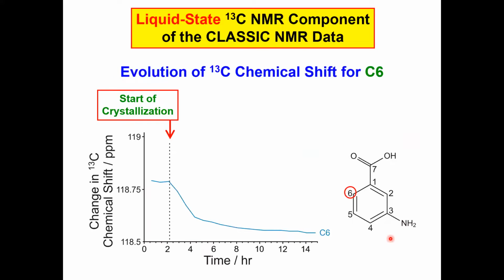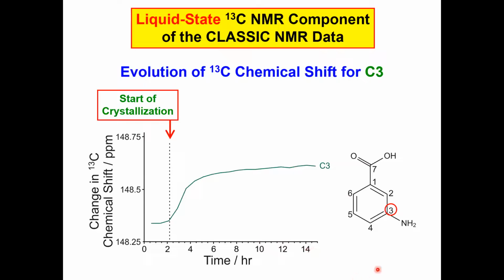So let's look first of all at carbon number 6. I'm going to show all of these results on the same scale of 0.5 ppm. So in the first 2 hours, when nothing is actually happening, the chemical shift is constant. And then, as soon as crystallization begins, the solution state chemical shift changes in a very well-defined way. If we look now at C3, the same thing happens, but in the opposite direction. No change in the first 2 hours. And then once crystallization proceeds, there's now significant change in that chemical shift.